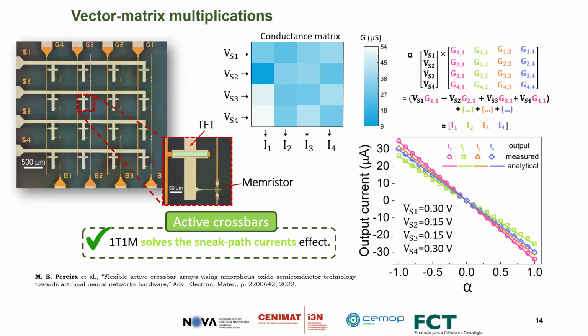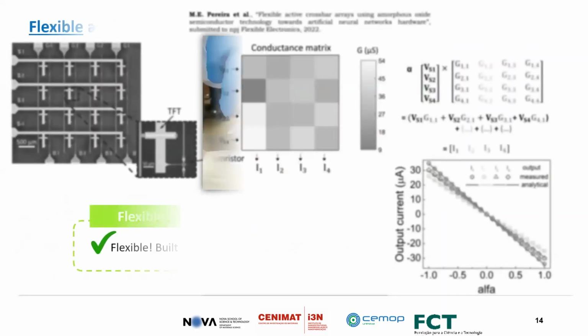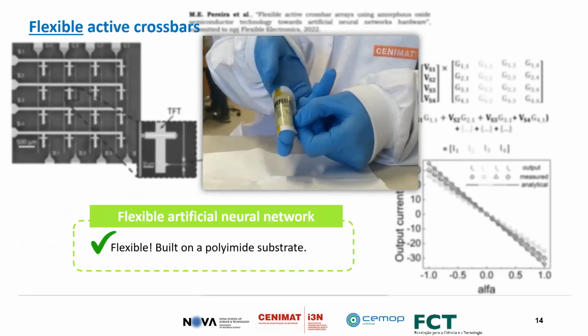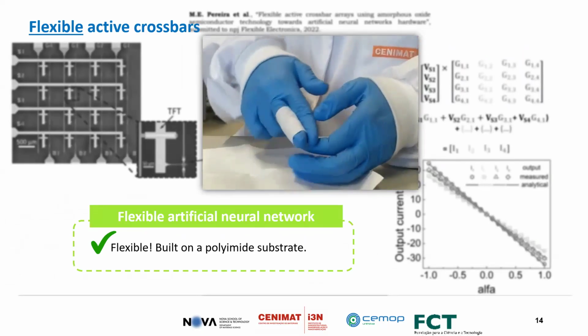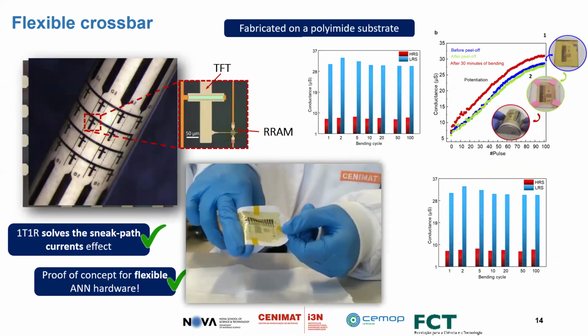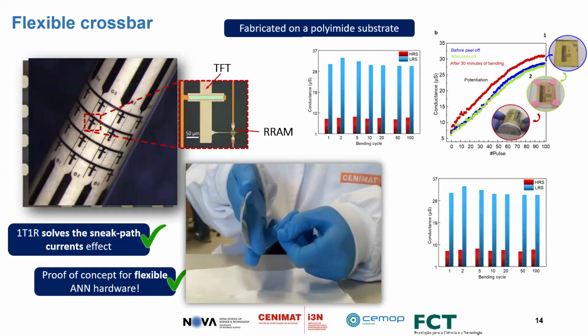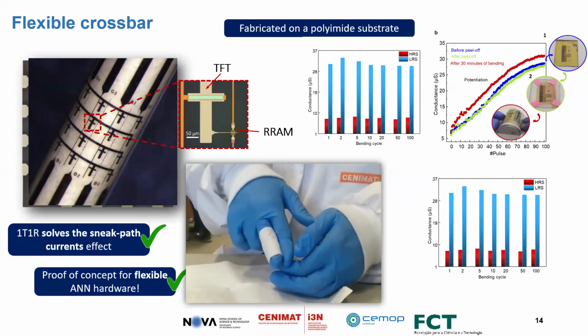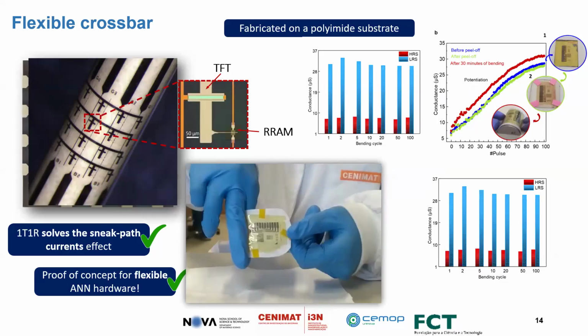Then as a proof of concept, we built an array size of 4 times 4, like 16 elements. And we show here that by adding a transistor to each resistive switching cell, we solve the sneak path, so there are no crosstalks between the units. We also show simple vector matrix multiplication using the voltage vectors here. Additionally, we implemented the same system on a flexible substrate, showing the proof of concept that it works because it's a low temperature process. We did certain bending tests, and we observed that it is reliable under the bending tests and still functional.